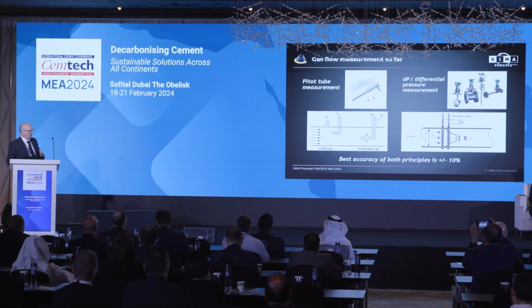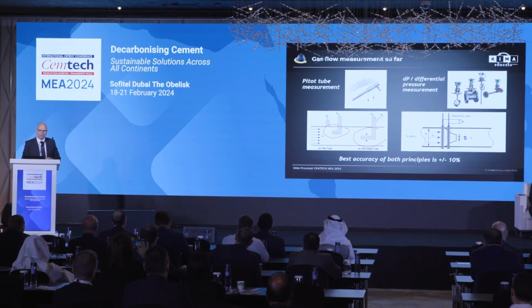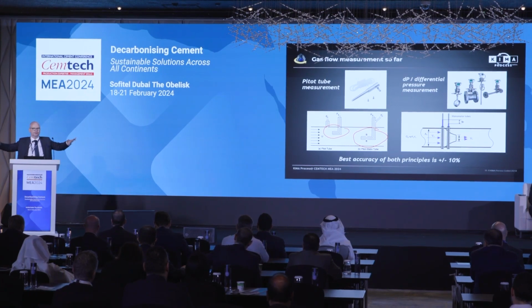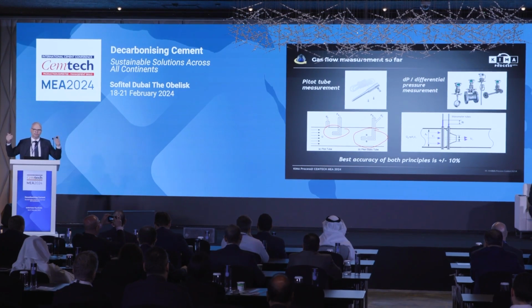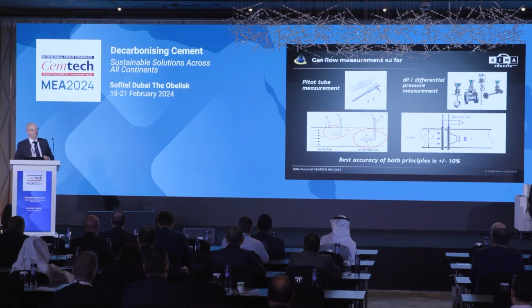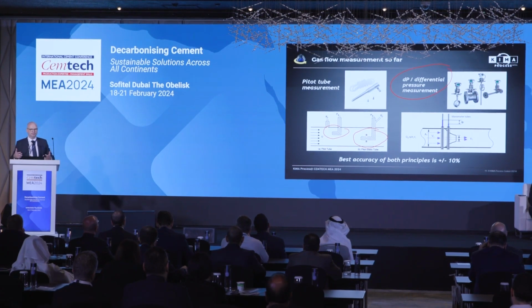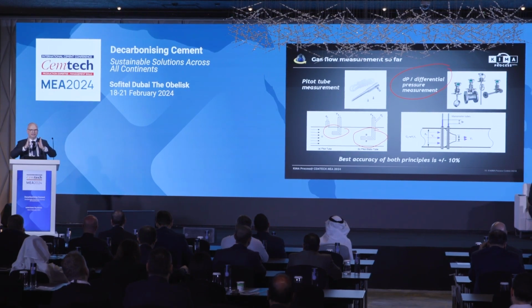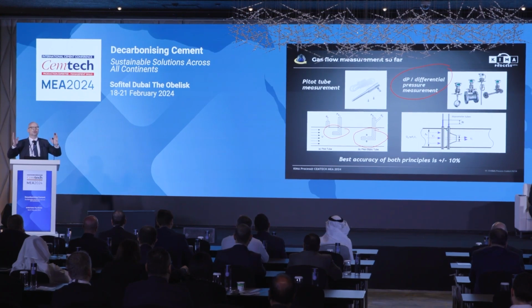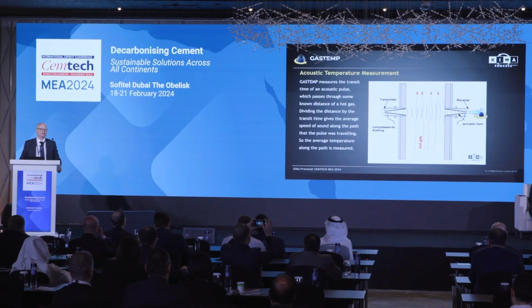And the gas flow measurement, also briefly explained: if you work with pitot tubes, they are very sensitive. You see that, by the way, these are the nozzles which you see on an aircraft, on the outside of the cockpit. There, pressure is measured, and also on the wings there are always these pitot tubes to measure the pressure. If you use that, it's very sensitive in view of dust and maintenance, of course. Similar if you use delta P. If you use a delta P, you know exactly that you have to change from one diameter to another diameter and to another diameter again. This means you slow down your gas flows. No need for that with the acoustic measurement principle, which works as follows.